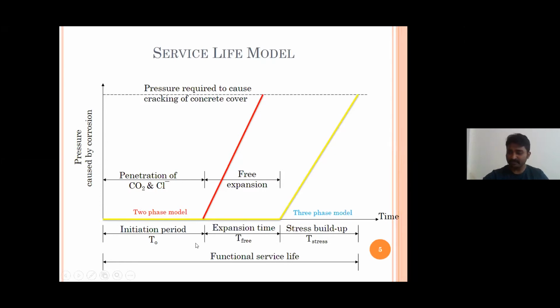After that there is the free expansion stage, and after that it is the stress build-up stage. So Liu and Weyers refined the two-stage model into a three-phase model. They incorporated the porous zone thickness in their model. And when people predicted the service life, it came very close to the actual service life of the structure. So here we find the importance of porous zone thickness.